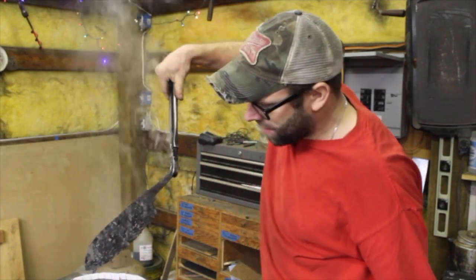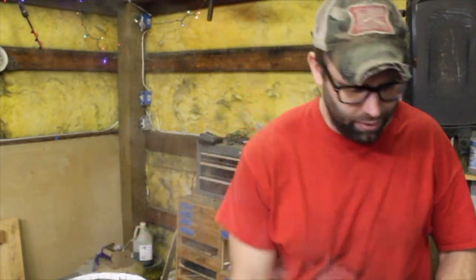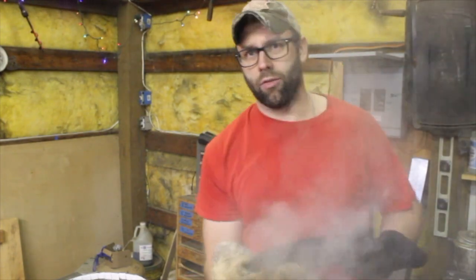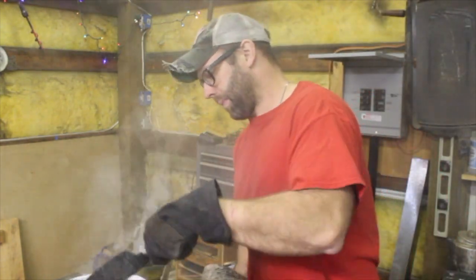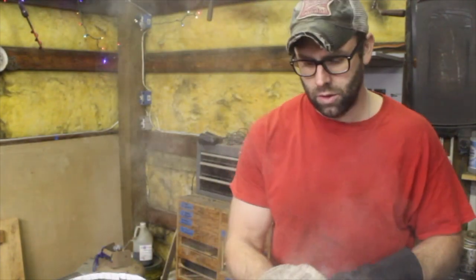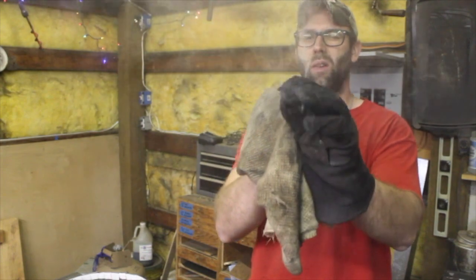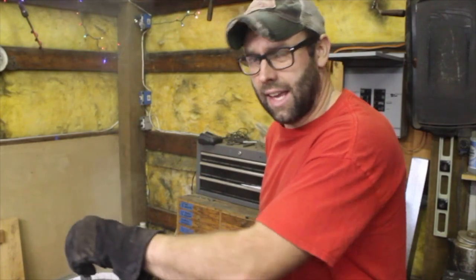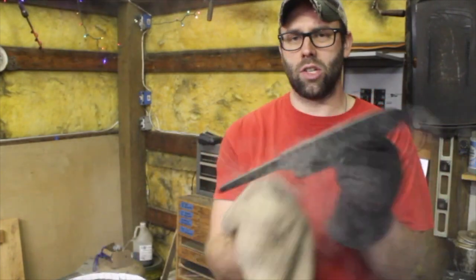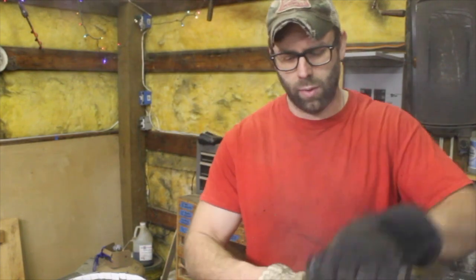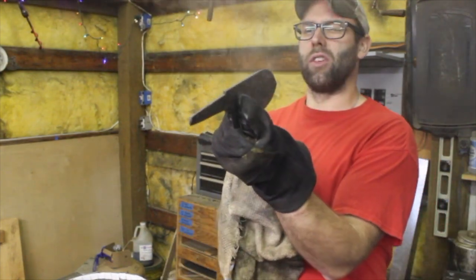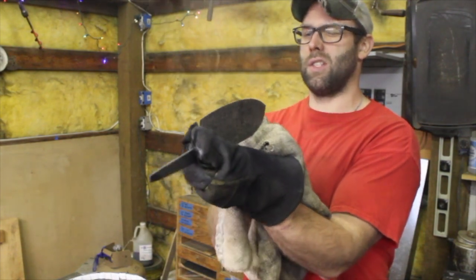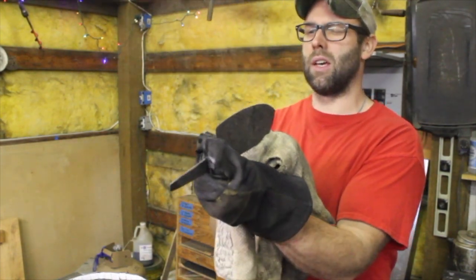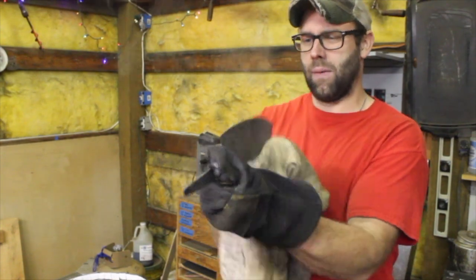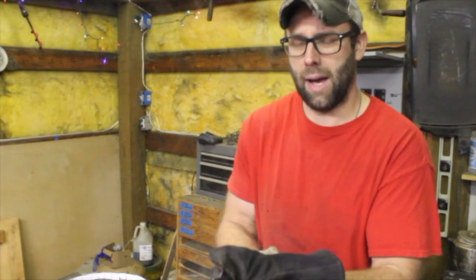So the key here is to get this quenched out far enough so that you actually attain hardness, full hardness, and are still able to utilize the window of time that you have to straighten it out. This is complicated with a thicker tang and/or spine that's not going to quench as fast as the rest of the knife. So you're dealing with two different dimensions and cooling rates and residual heat. So it's all a balance game, really.